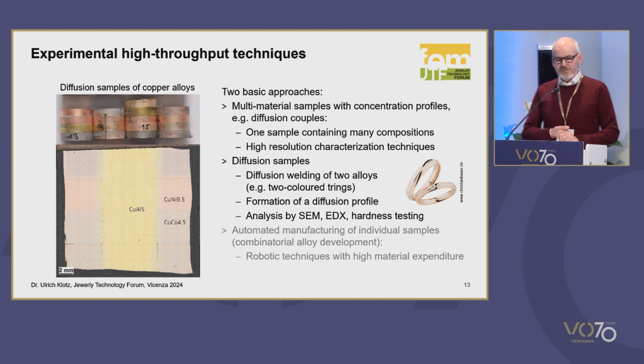One is so-called diffusion couples. We all know colored jewelry with 2 or 3 different colors, like the wedding bands that are shown here. And these rings are usually bonded by diffusion bonding. So you put 2 metals into contact at high temperature with some pressure, and then some diffusion is taking place. The atoms are mixing in a very small zone, and this gives a stable bond of these 2 alloys.